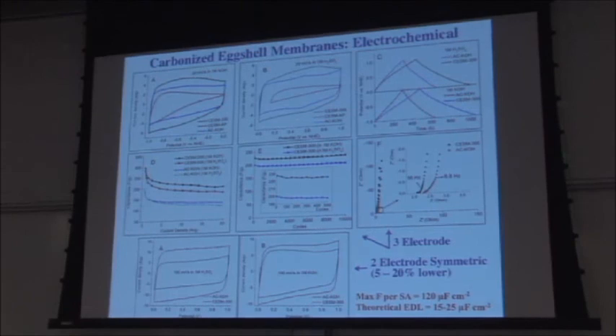You have a capacitance in KOH as high as 300 farads per gram. And it drops, but even at a high current density of 20 amperes per gram, you have a capacitance of about 225 farads per gram. Cycling stability, remarkably stable. So again, in KOH, basically, well, in either one, you lose less than 2%.